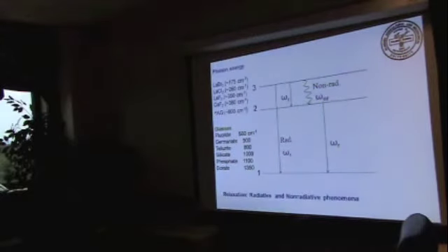If this energy gap is, let's say, 2000 wave numbers, and the material is something like lanthanum bromide, you need more than 10 phonons to fill the gap. So that becomes a higher order perturbation. So that particular non-radiative relaxation doesn't happen. Then the electron will jump down to here, and you only see light coming out, depending on the energy gap. So in solids, excited ions relax either radiatively or non-radiatively.